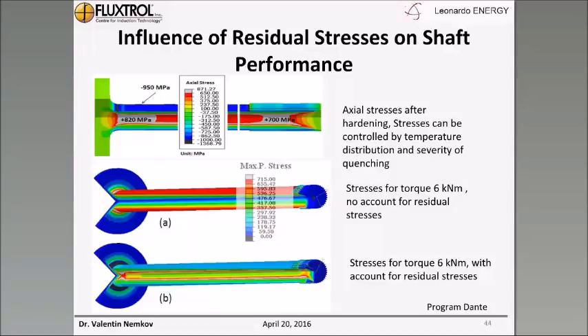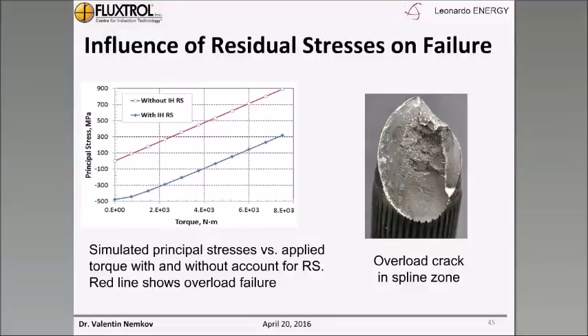And here we have results of simulation of loading of this shaft, loading by application of torque to the spline. Here, in this case, we have stresses in the axle when applied 6 kilonewton meters torque without account for residual stresses. You can see here big tensile stresses on the surface. If we make a similar simulation with initially generated residual stresses, we have an absolutely different situation. Even on the surface, we have almost neutral or slightly compressive stresses, which definitely can result in higher loading capacity or longer lifetime of the part.